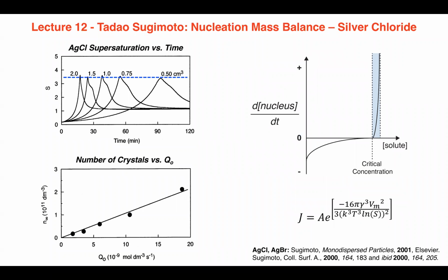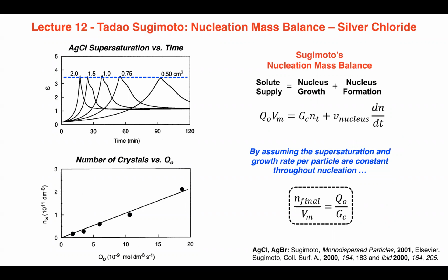Right. The part of that doesn't really appear in this much at all is the nucleation rate. You know, we just said, let's just call it a step function. It doesn't even matter what its true form is. As long as it's pretty strong dependence on concentration, you're going to get this sort of a relationship where the number is really dominated by these two terms. Nucleation is kind of an unimportant reaction in these processes, it turns out.